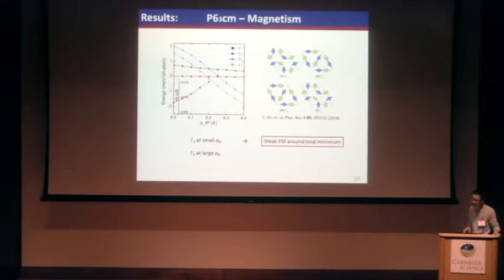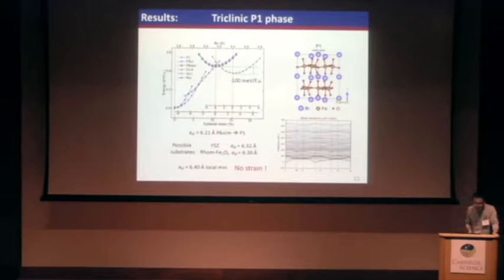And also for the magnetism, we consider the 4 typical non-collinear magnetic configurations, and the ground state at smaller in-plane lattice constant has the gamma-2 configuration and allows for the canted weak ferromagnetism. Then at even larger in-plane lattice constant, we notice there is another phase here. Again, I should stress that the local minimum is out of those curves. So if, again, this phase can be stabilized, there should be no strain here. The phase looks like this.